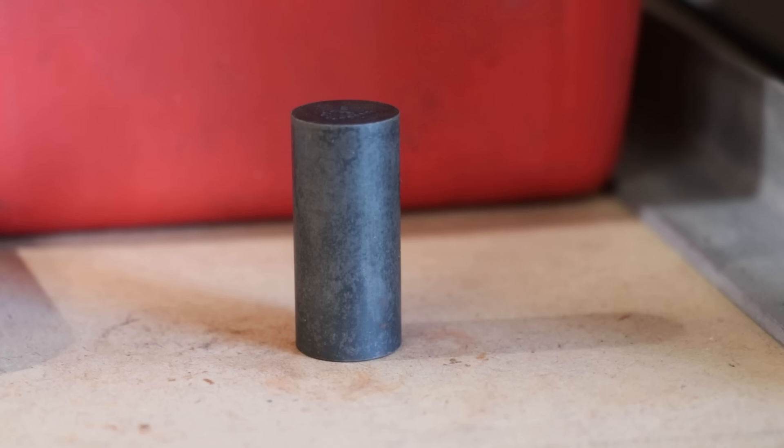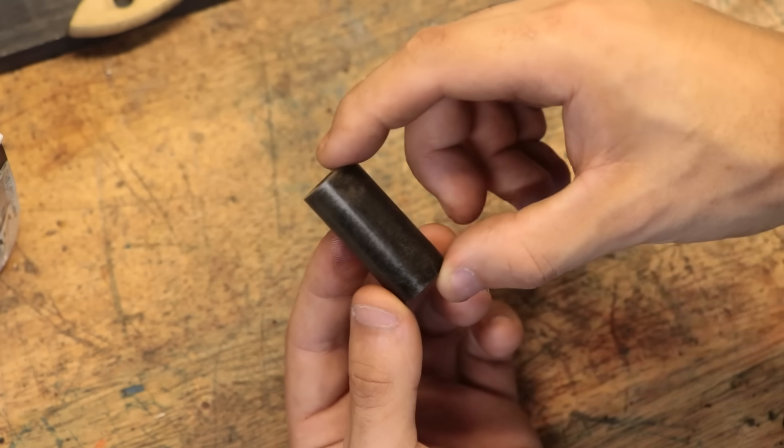The hot oil bluing has also worked out quite well. It's developed a few spots of rust, and that's mostly around the areas that suffered a small amount of damage and the bluing flaked off. The rust bluing however seems to have worked out the best. It stopped most of the corrosion from forming, however it did discolor from that dark black to a more grayish color.